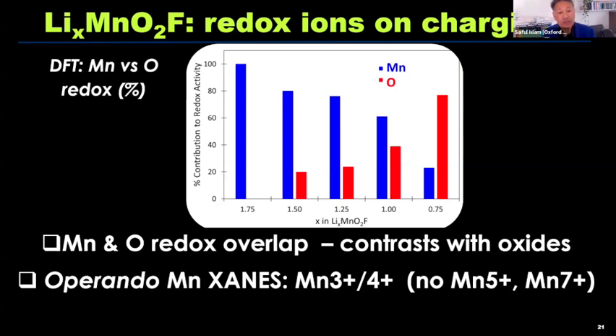And that agrees with experiments such as X-ray absorption near-edge spectroscopy, which can look at oxidation states, confirms 3+, 4+. But as you increase the charge, this red bar begins to increase, and that red bar is oxygen redox. So there is a mixture of manganese and oxygen redox within the material, and at the top of charge, on your right, it's dominated by oxygen redox. This behavior contrasts with layered oxides, where there's a strict transition between transition metal redox and oxygen redox. From experiment and simulation, we don't find any evidence of high valence manganese, 5+ or 7+.